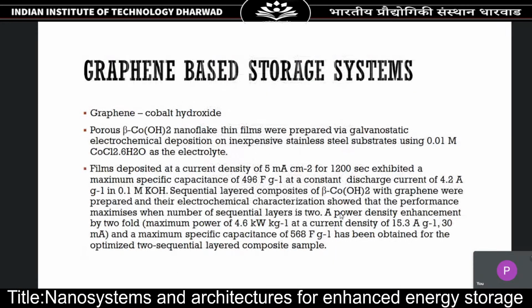Coming to graphene-based storage systems, one of the interesting systems we studied was graphene cobalt hydroxide. Cobalt hydroxide is a very unique nanomaterial in that it has a layered structure, right? So what we have done is we have taken porous beta cobalt hydroxide nanoflake thin films, and they were prepared by galvanostatic electrochemical deposition on a stainless steel substrate. The starting material was cobalt chloride hexahydrate, and we could get a capacitance of 496 farad per gram at a current density of 4.2 ampere per gram, and the electrolyte used was potassium hydroxide.